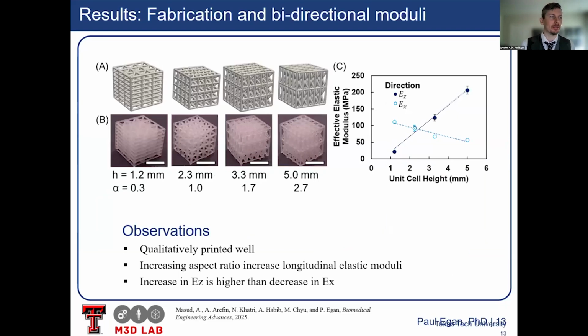And our preliminary results, so we did different aspect ratios of the unit cells and formed them into lattices that were roughly the same size. And you see here with the effective elastic modulus that EX in the transverse direction goes down as you increase that unit cell height. But in the longitudinal direction that's aligned with the loading, you get an increase in that effective elastic modulus. And so that increase in the elastic modulus is coming at a steeper rate than the decrease in the transverse modulus, which is a good sign because that's showing you're overall more mechanically efficient for the amount of weight and material that you're putting in the body.